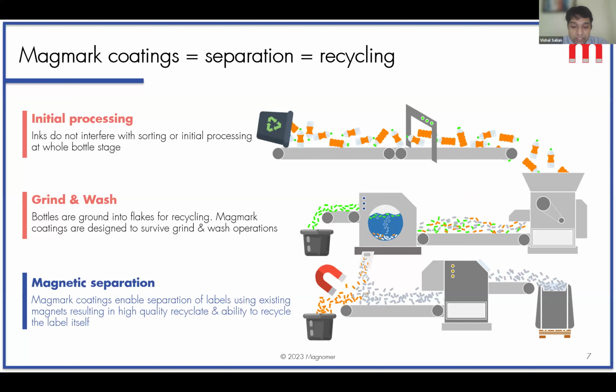Shrink sleeves made of PETG and PVC sink with the PET flake, becoming contaminants. What Magnomer does is it uses magnetic separators that are present downstream from here, and it sorts out the label without hindering any of the operations upstream of the magnet. This results in clear PET flake that can then be recycled back to bottle grade.